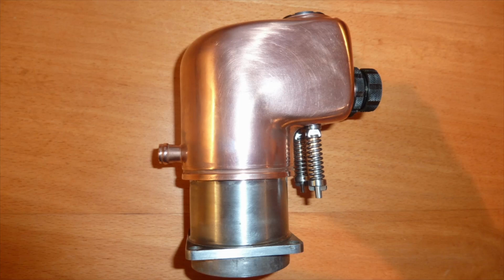Each one was done separately, as I mentioned before, as I had a limited amount of alloy and needed to learn the process as I went along. An early test for air tightness revealed that all was well at the joints, while tapping with the fingers all around suggested sufficient strength and thickness.